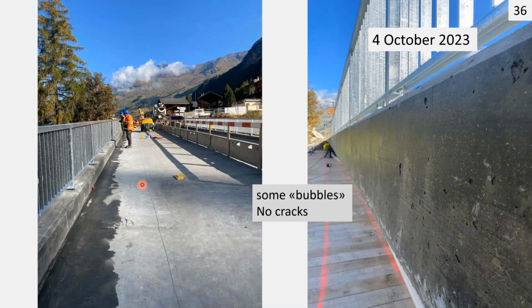Now let's have a look at the results. You see on the right-hand side the UHPFRC surface of the curb some days later, on October 4, and there are some bubbles just in this zone. So this can occur, that sometimes there are some bubbles, but it's just the same like for concrete. But the other surfaces are without bubbles. And also, of course, we are looking after cracks, and usually there are absolutely no cracks.